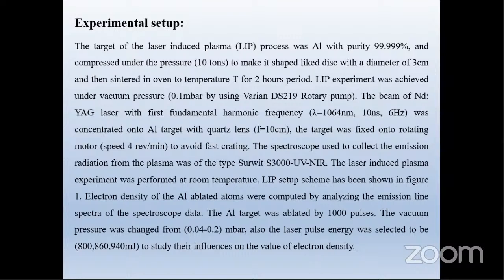The target of the laser-induced plasma process was aluminum with purity 99.999 and compressed under the pressure of 10 tons to make it shaped like a disc with a diameter of 3 centimeters, and then sintered in an oven at temperature T for a 2 hour period. The laser-induced plasma experiment was achieved under vacuum pressure of 0.1 millibar by using a Varian DS 219 rotary pump. The beam of a neodymium YAG laser with first fundamental harmonic wavelength lambda equal to 1064 nanometer, 10 nanoseconds, 6 Hz, was concentrated onto the aluminum target with a quartz lens, f equal to 10 centimeter. The target was fixed onto a rotating motor at speed 4 revolutions per minute to avoid fast cratering.